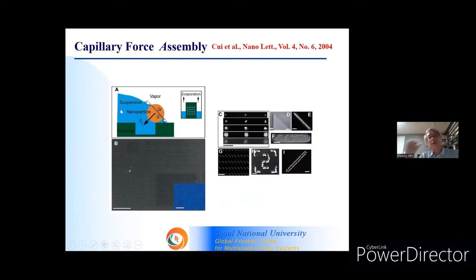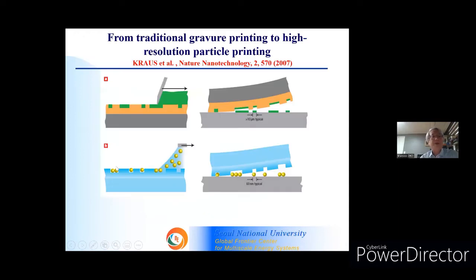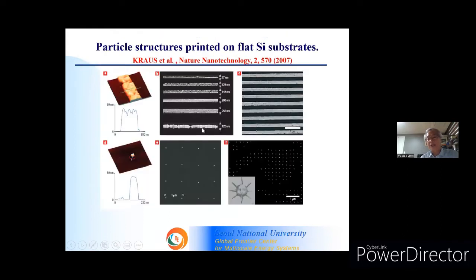Capillary force can be effectively utilized to introduce nanoparticles into pre-patterned areas to make these kinds of nanoparticle patterns. If you want to make a first pre-pattern, then you can easily make nanoparticle patterns. Or nanoparticles trapped inside this pre-patterned area can be used as a stamp to transport nanoparticles onto a flat substrate. It's similar to gravure printing.